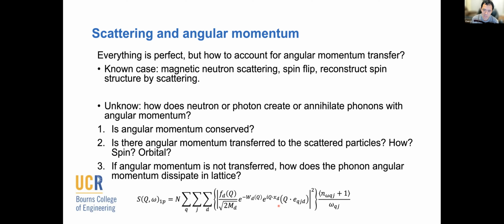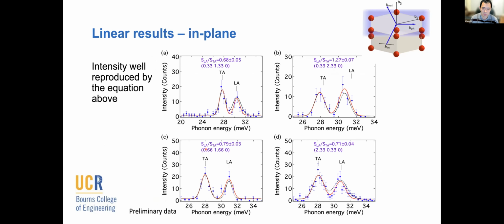If there's such a transformation, if there's such a transfer, does this affect the overall dynamic structure factor we are seeing here? It turns out the answer is both yes and no. It depends. This is actually our first experiment, and we thought we should be able to see some anomaly by scattering X-rays off those transverse acoustic and longitudinal acoustic phonons, as we showed previously from the calculation. But we didn't observe any disagreement from our calculation.